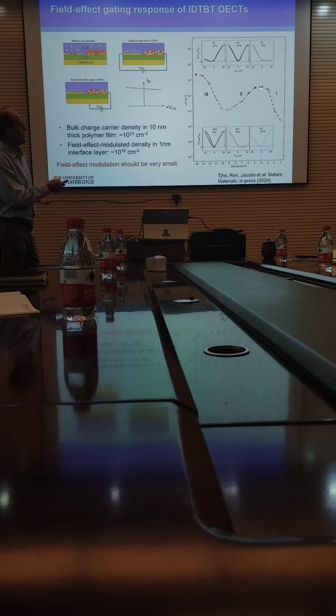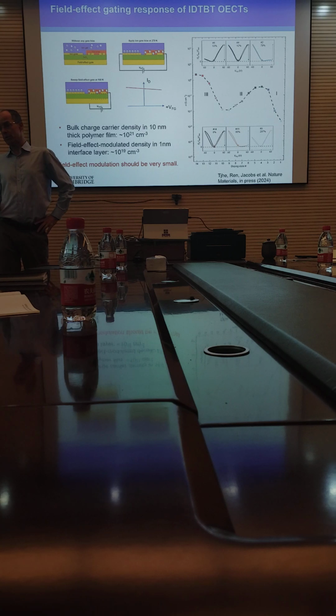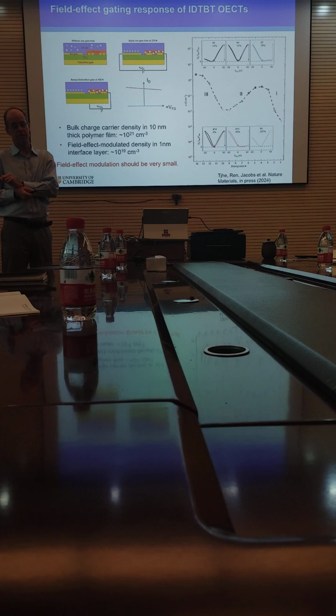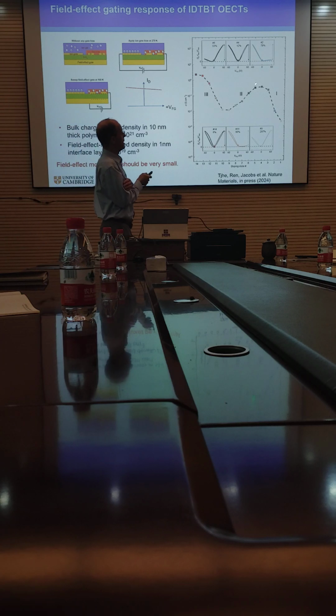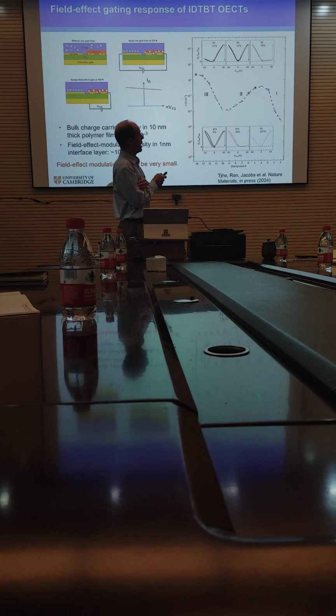And let's focus maybe on this point here, which is the peak in the conductivity. What we thought we would see at this point, for both negative and positive gate voltage, we thought we should see a small decrease in the current. Because with the ion gate, if at this point you apply a bit more p-type doping, the current drops. We thought if you apply a negative gate voltage that is also a little bit more p-type doping, the current should drop. The other direction, again, the current should drop as well.